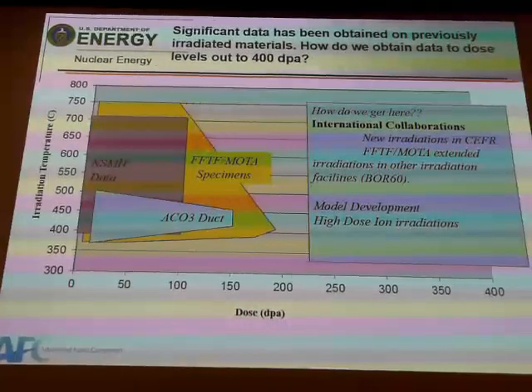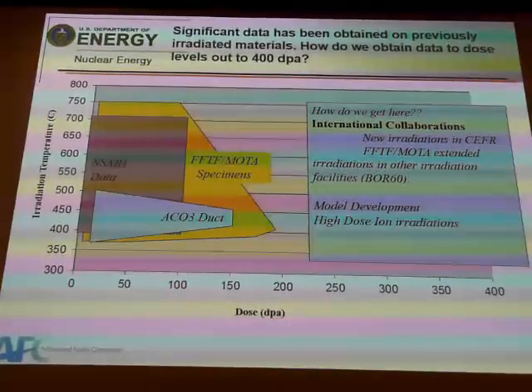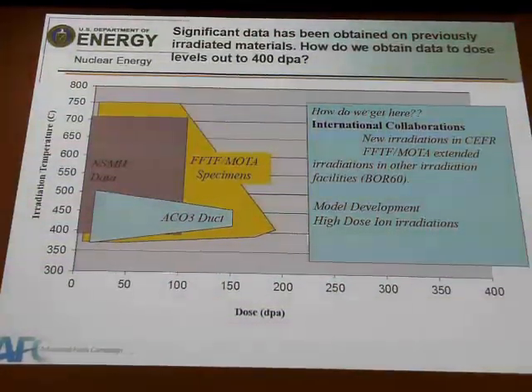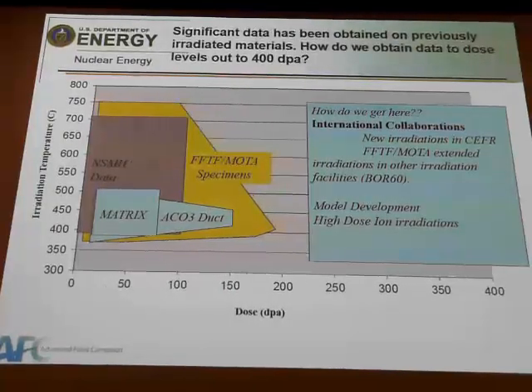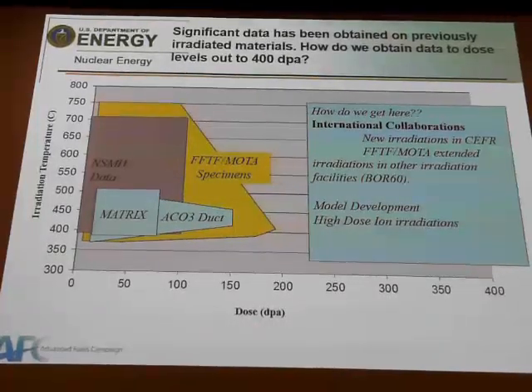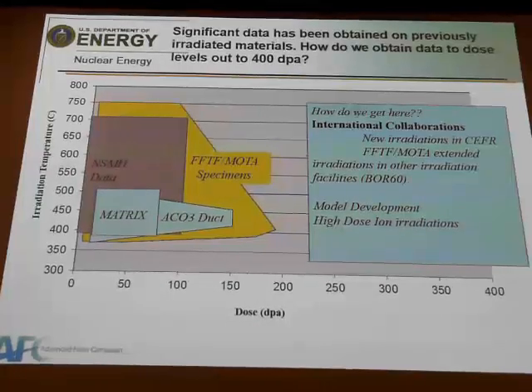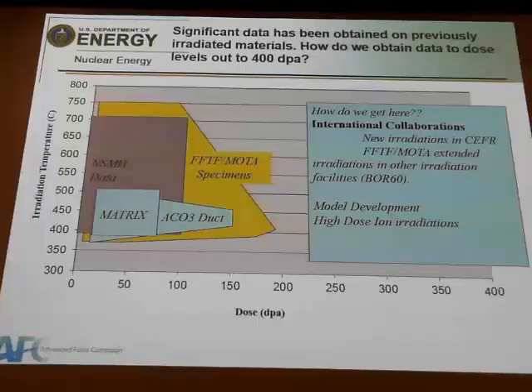These are more materials that we actually retrieved from FFTF MOTA, which is Materials Open Test Assembly irradiations. So that gets you out to almost 200 DPA. And then this new irradiation we just did in France, called the MATRIX irradiation in the Phoenix reactor, that's new material out to about 75 DPA. So none of these are really getting us out to this 400 DPA that we would like to get to.